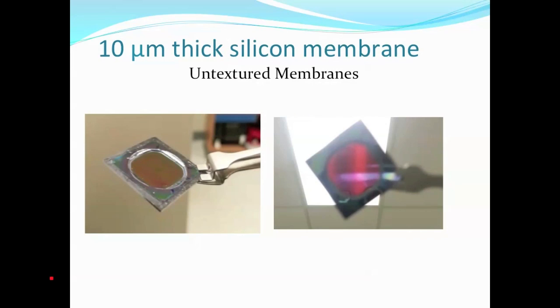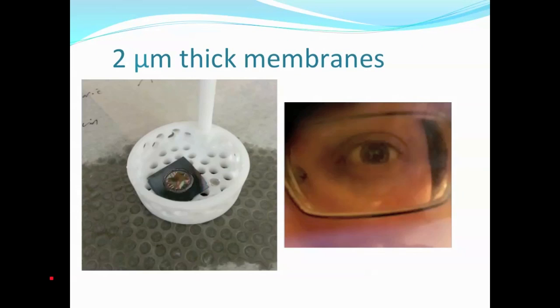I don't know if these pictures come out very well or not, but you can see that it is partially transparent. So this is a picture of an untextured 10 micron membrane. The membrane diameter is about 1 centimeter. And using this process, we can actually fabricate membranes down to 2 microns. So here, on the left is a picture of a 2 micron membrane. And then on the right, it doesn't look like it came out very well, but I took a picture of my eye through the silicon.